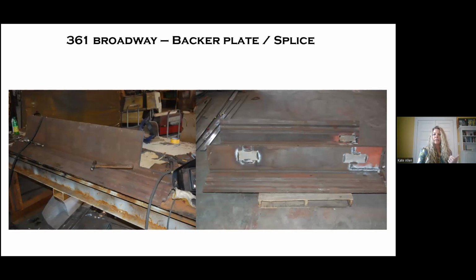Again, the deteriorated cast iron is going to be cut out. The new filler piece is going to be put in to match the profile. It's welded around the perimeter, and then the cosmetic repairs follow. But typically we use stainless steel for backer plates, and that should always be isolated with like a 3M Scotch wrap or a neoprene, and that prevents galvanic corrosion. And then finally, the DevCon is a visual repair, where the backer plate is the structural repair.